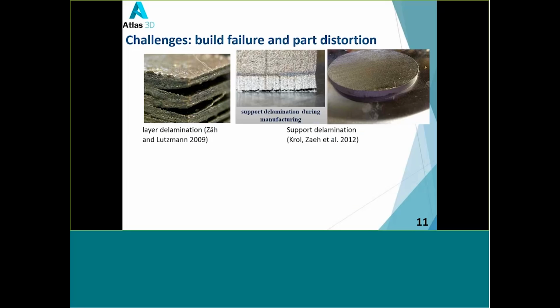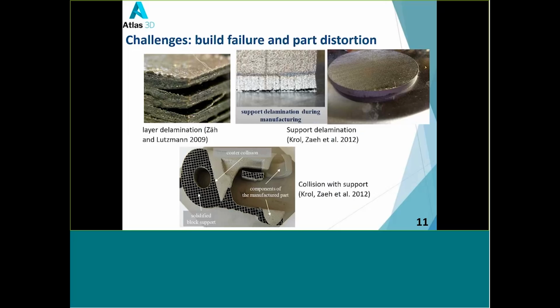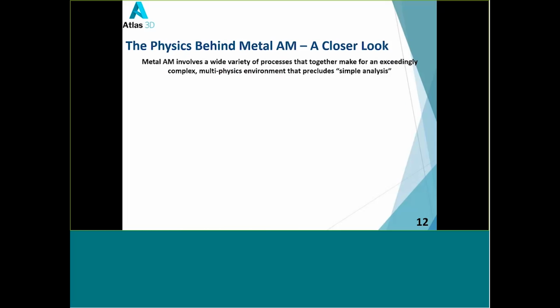The delamination is a very serious problem in the powder bed fusion process. You can see that when you build a part, if you have a delamination of the support structure from the build platform, you will have very large part distortion even during the build process. And when your recoater blade is trying to spread a new layer of metal powder, it will collide with the distorted part, and this will stop the build process, and you need to start everything from the beginning. So in order to solve those problems, we need to understand what's the physics behind the metal AM process.